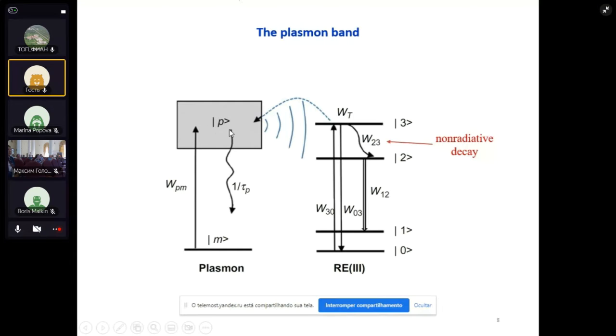is that when we are dealing with the influence of a plasmon band from metallic nanoparticles on an emitting rare earth ion, for example, we have discovered that there is a strong competition. There should be a balance between mainly what we call local field enhancement, if we have good resonance conditions with the plasmon band of the metallic nanoparticles, but also we have non-radiative energy transfer from the emitting ion to the plasmon band. And this is a very important channel.